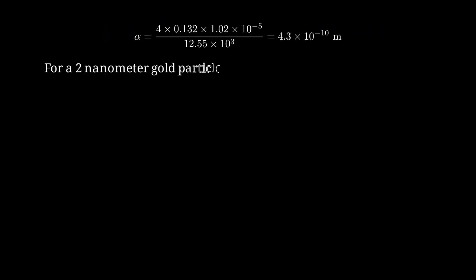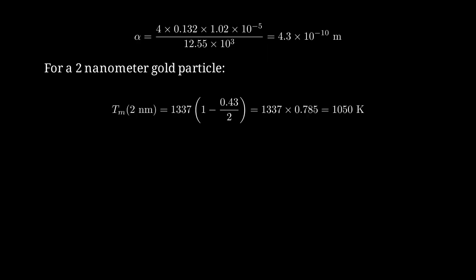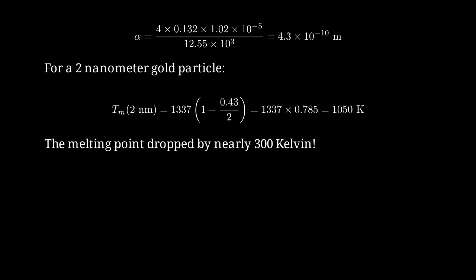Now let's calculate the melting point for a 2 nanometer radius gold nanoparticle. Tm of 2 nanometers equals 1337 times 1 minus 0.43 divided by 2, which equals 1337 times 0.785, giving us 1050 Kelvin. That's about 777 degrees Celsius. The melting point dropped by nearly 300 Kelvin just by reducing the particle size. This is a huge effect.